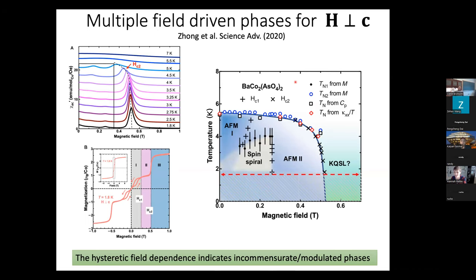That's a good point. I think our intuition is formed by the experiences that we've had over the years, and what I'd say is that having this kind of hysteretic behavior in an antiferromagnetic system... The hysteretic behavior is quite familiar, obviously, in ferromagnets, where it has to do with the motion of domain walls in the material. So a very complicated structure that arises out of dipole interactions, essentially, in a ferromagnet. So you need that kind of complexity to have bistability in the magnetic system. And so if I find an antiferromagnet with this kind of hysteresis, I would say that I have some kind of a very complicated landscape of different kinds of orders that I'm selecting between with the applied magnetic field.